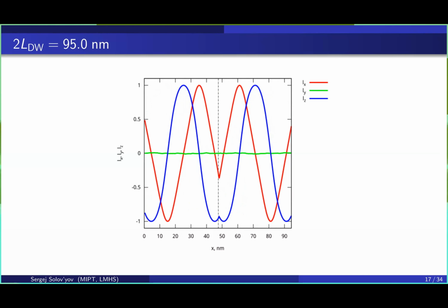The inter-domain distribution of the Néel vector changes, and it also changes the boundary states at the ferroelectric domain wall position, and the internal magnetic structure. The periodicity of the spin spiral decreases, but an additional half of a period of this periodic structure adds to the distribution.